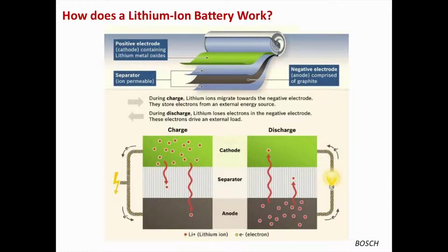So now this layer acts as a passivation film, which is very important for the functioning of lithium-ion batteries, because it has to be electrically insulating, but it should be lithium-ion conducting, so that the lithium-ion battery is functioning, but it stops the further reduction of the electrolyte. So SEI stability is very important when we talk about lithium-ion batteries and their long-term cyclability. And given all the requirements of the automotive industry, that it has to go through more than 99.9% of cyclic efficiency, this is a very important step in achieving that.